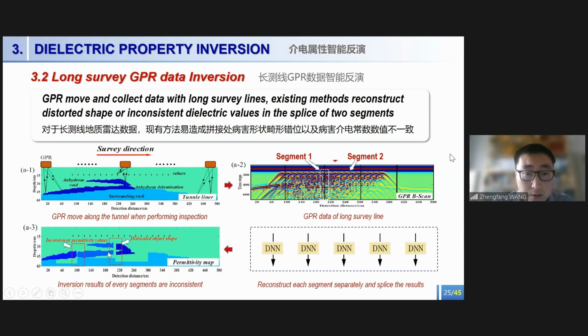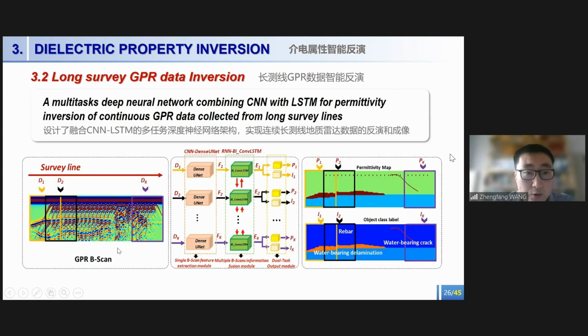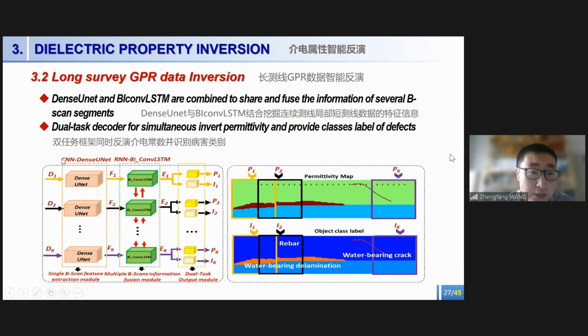So in order to solve this issue, we proposed a multitask deep neural network that combines CNN with LSTM for permittivity inversion of continuous GPR data collected from a long survey line. Specifically, we use a DenseUNet and bi-convolutional LSTM to share and fuse information of the several B-scan segments. Then in the decoder, we design a dual-task decoder to simultaneously invert the permittivity distribution and provide the class label of the defect.